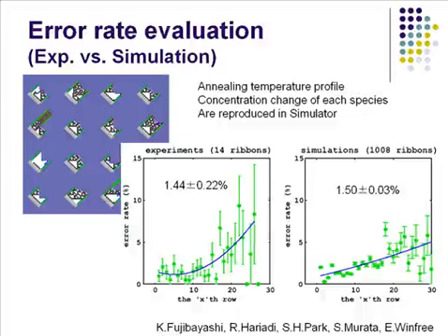And if you see this part, the error bar is quite large, and the error rate itself increases rapidly. But in the simulation, we do not have such phenomena. The large error bar is because around here the crystal growth is actually stopped because of the lack of the monomer DNA type.